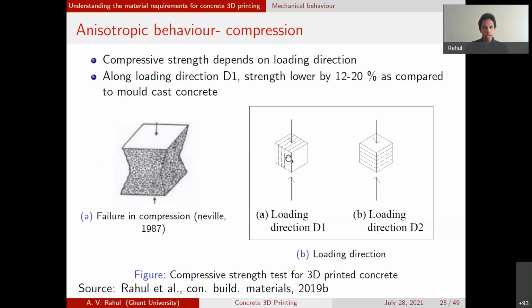So if you have an interlayer existing like this, parallel to the loading direction, it's easier for the concrete to bulge out and move out laterally. Therefore, you would see a more premature failure when you have the layers aligned in this direction. On the other hand, if the layers are aligned in this direction, you don't have an interface like this that allows easy lateral movement or easy bulging out of the concrete. Because of that, you see a relatively higher compressive strength when you load it in this direction.